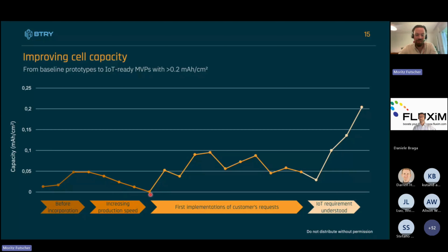But then we also learned to handle these new recipes to fabricate cells with a high capacity at a high speed. And here you see the performance was a bit all over the place. And this was really our first interaction with customers, building cells according to the customers' requests, where we see a lot of fluctuations in the performances. And then at some point we also understood and standardized our cell design. And you see that now we're really increasing the capacity. We're already above 0.2 milliamp hours per square centimeter. And this is now already enough for many IoT applications. And these are cells which we already ship out to customers for first validation and also integration into devices.